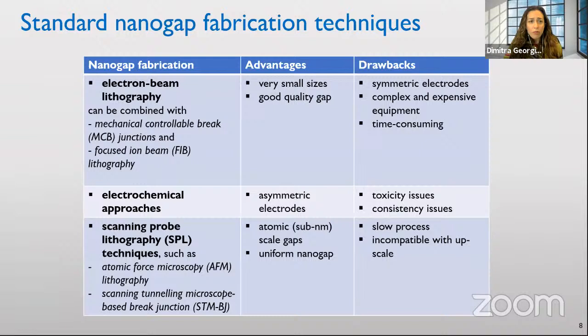So the standard nanogap fabrication techniques are electron beam lithography, which can be combined with mechanical controllable break junctions, and focused ion beam lithography. Advantages are that with e-beam, we can actually get very small sizes and good quality gaps. However, most of the time we get symmetric electrodes, or we need to make the fabrication even more challenging and complicated to have asymmetric electrodes by adding several lithography steps.